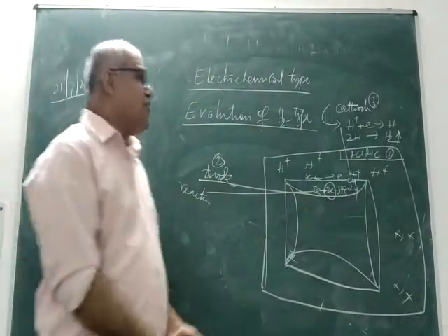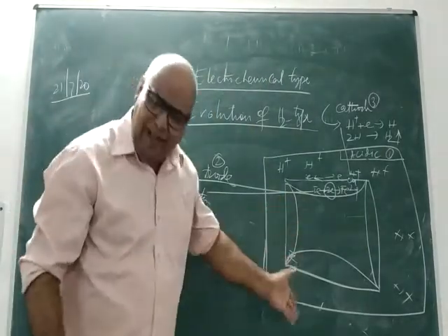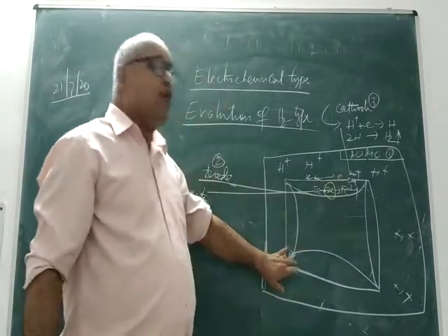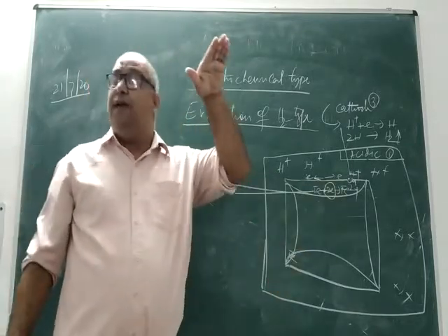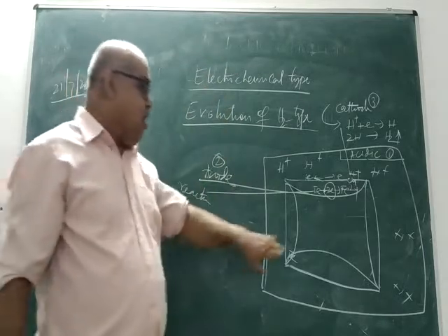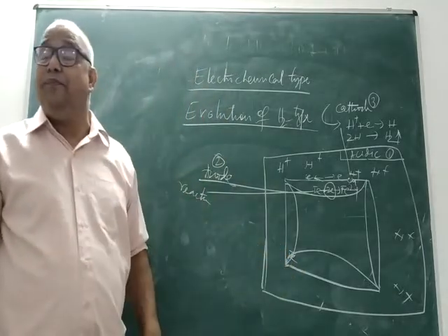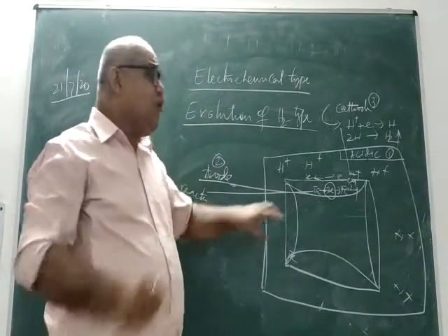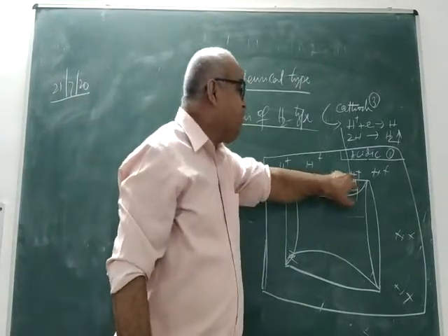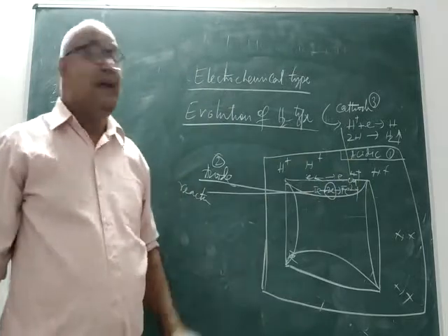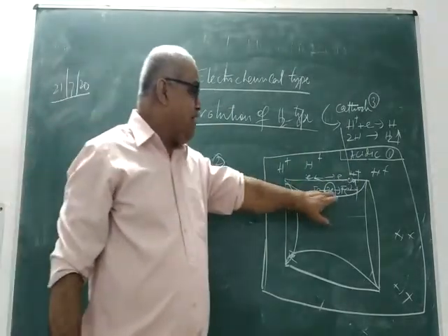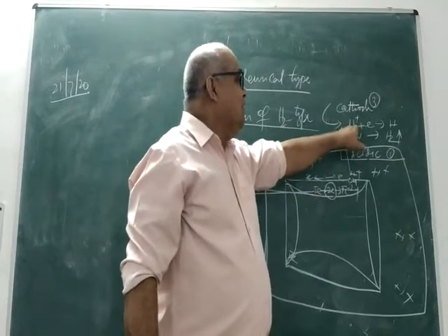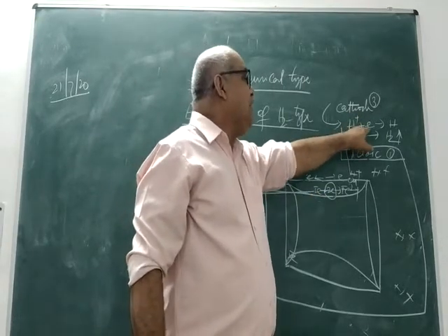So since it is a metallic structure made of basically iron, but some kind of impurities like copper is there, iron stands higher than copper in the electrochemical series, so automatically iron will become your anode. The entire metallic surface will become your anode, and where copper is present, it will become your cathode. At anode, loss of electron will take place, as we have discussed earlier.